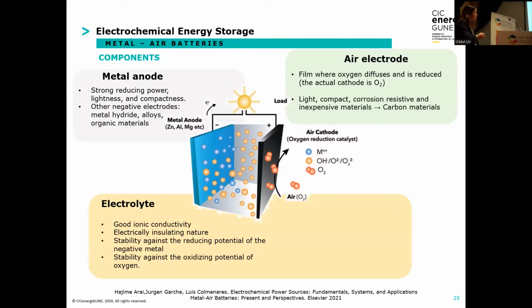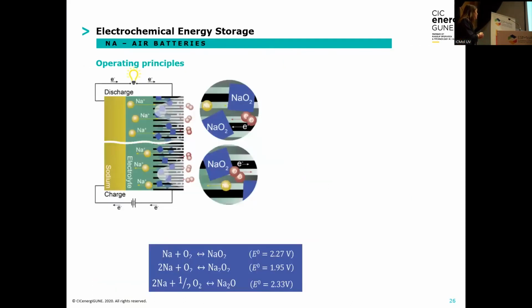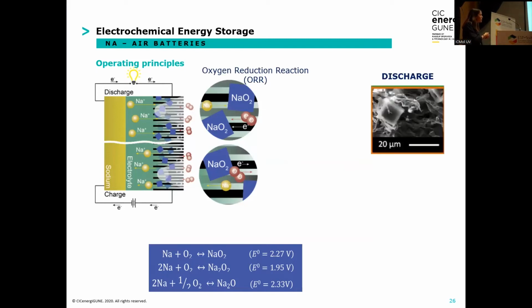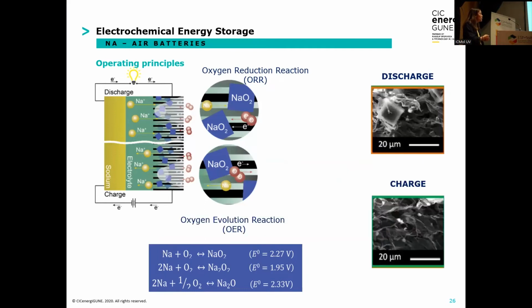Today I will focus on sodium oxygen batteries. In this kind of batteries, we have a sodium metal, a sodium conducting electrolyte and an air cathode. So what is happening during discharge? Oxygen is reduced on the surface of the cathode, and the sodium is oxidized. And then they combine to form, in principle, this kind of oxide where the energy is stored. So when we discharge, we form sodium superoxide on the surface of the carbon cathode, and this is where the energy is stored. And this reaction is reversible upon charge.